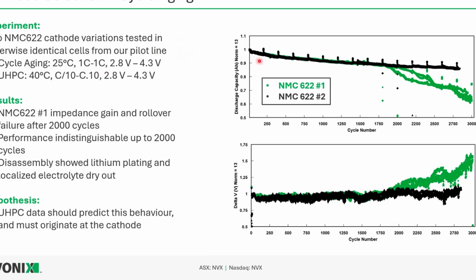So you can see here cycle aging on these 622 graphite cells that we made on our pilot line, cycling fine for 2,000 cycles, and then all of a sudden this group number one starts going into rollover failure. And then even looking at impedance values, looking at this delta V, in our case, delta V is average charge minus average discharge voltage of the cycles. There's actually no sign of anything going wrong here either until about 2,000 cycles. There was nothing in the data that we could see that would point to anything happening.